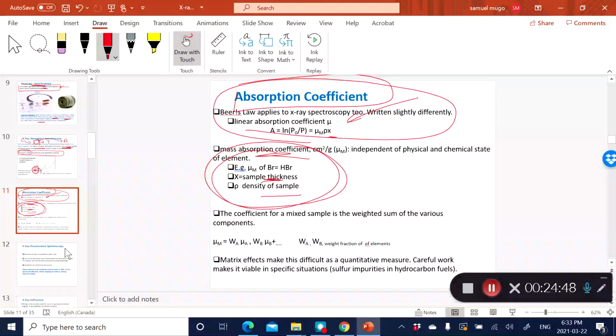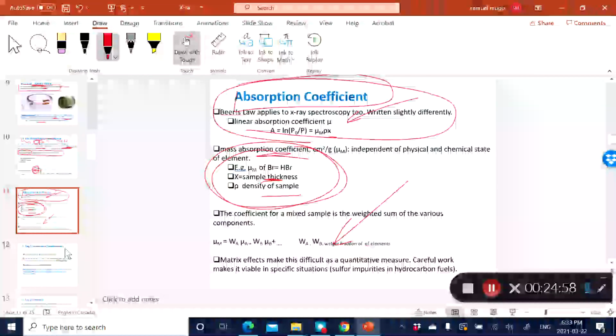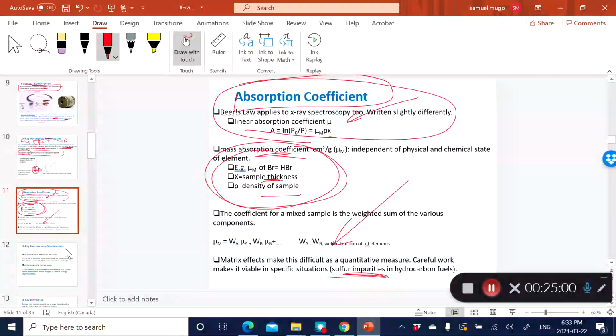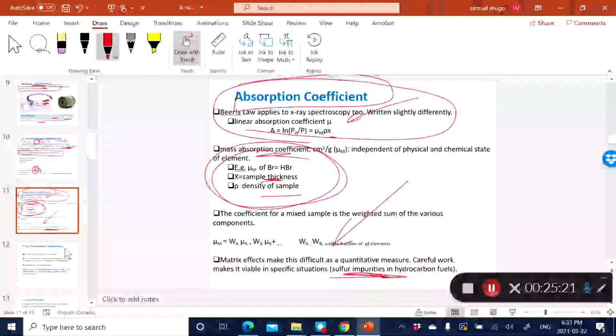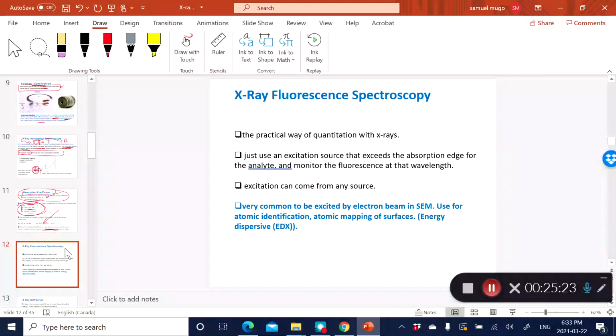Now, X-ray absorption spectroscopy tends to be very severely affected by matrix effects. Again, that's why I said it's not a very analytically useful technique, other than in very specific cases, such as analysis of sulfur impurities in hydrocarbon fuels, just because sulfur tends to have very, very specific K, L, and M lines, and as such, it tends to be useful for that application.